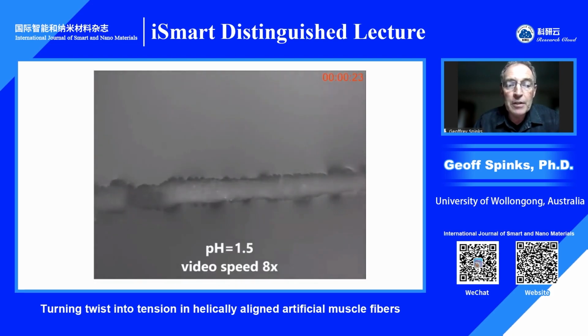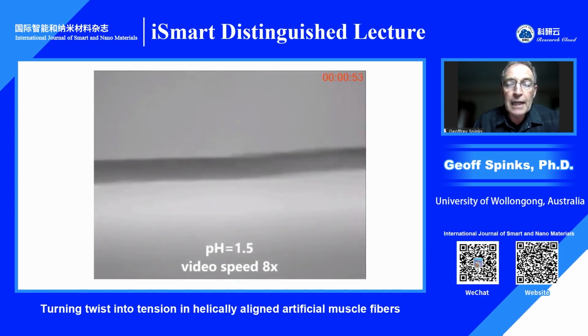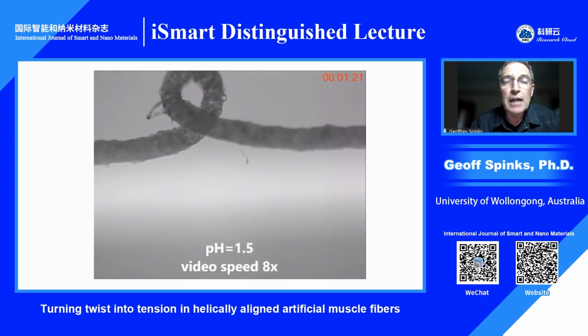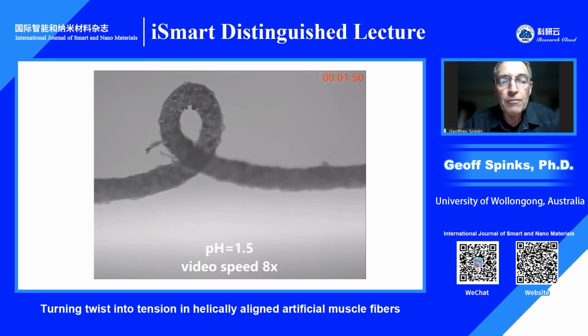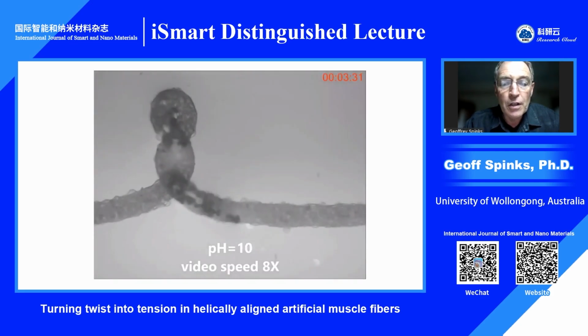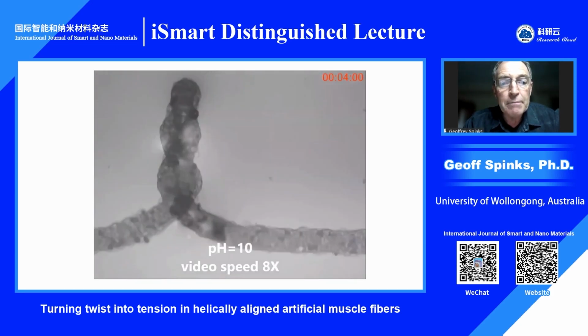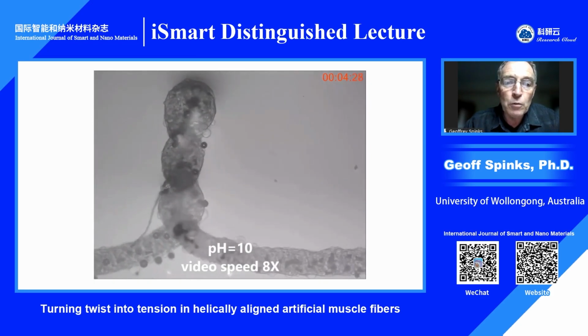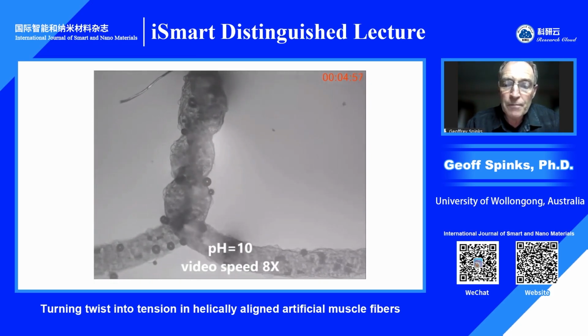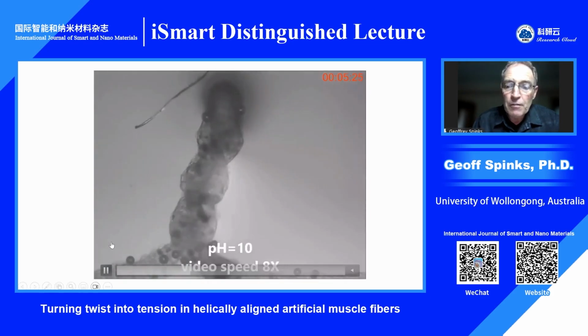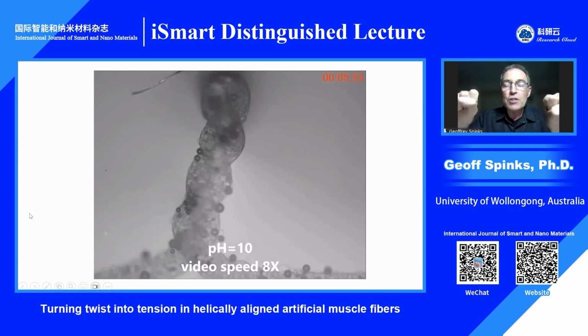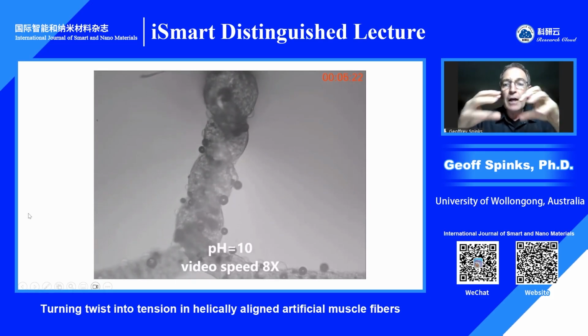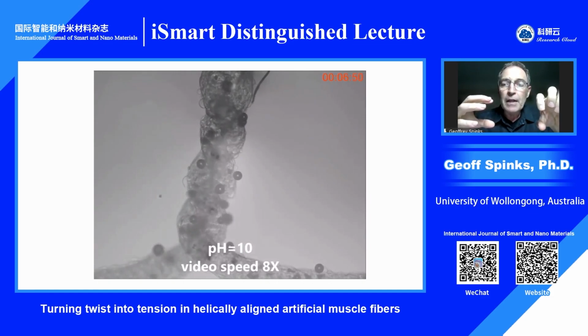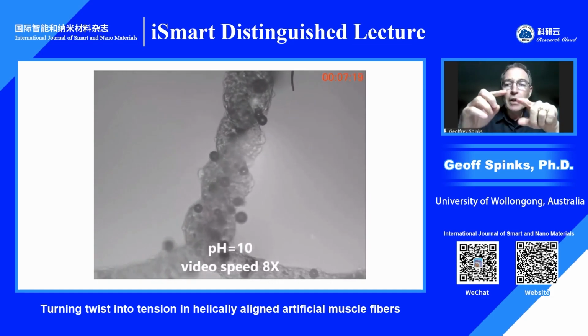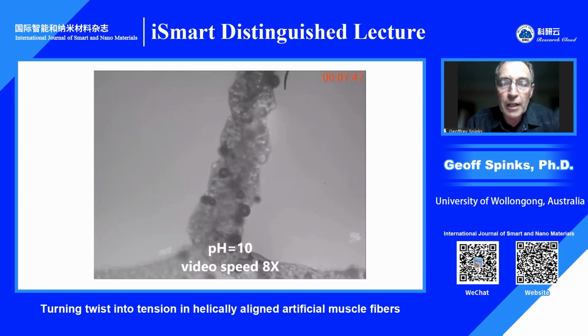About 100 micron diameter fiber, so certainly macroscopic. Here it is swelling in acid, and look, there is a plectoneme loop forming. The very first example of supercoiling without inserting any twist. Now we're swelling, further swelling in base, and you can see that that forms into a beautiful plectoneme, a multi-turn plectoneme structure. It's occurring because the fiber wants to untwist, but because it's clamped at both ends, it's building up a torsional elastic energy. Now that can be released by forming a loop, and then the loop twisting around itself, plying around itself as shown here.